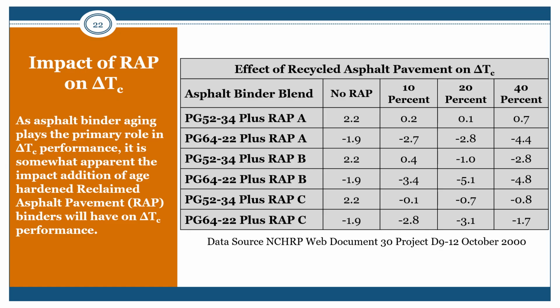This gives a general idea of the impact of RAP on asphalt binders with respect to delta Tc. You can see that most of these either have lessening positive numbers or wider negative numbers of delta Tc. This was RAP in two different binders, three different RAPs, to give you the example of three different RAPs in two different binders.